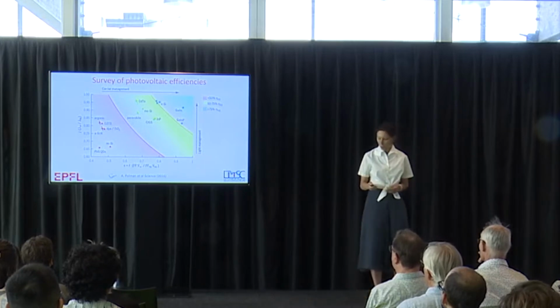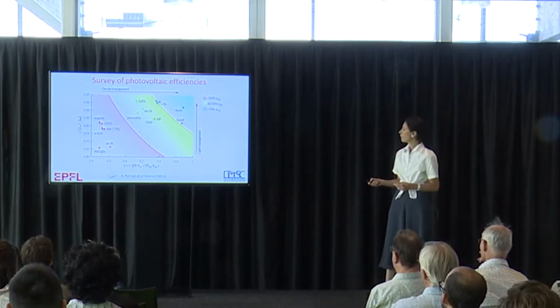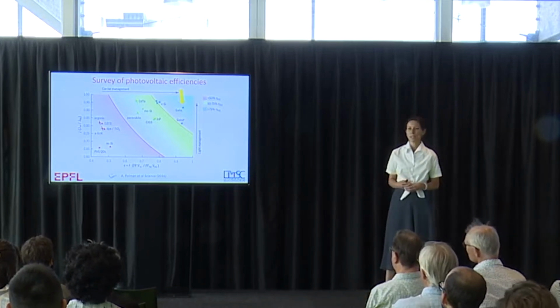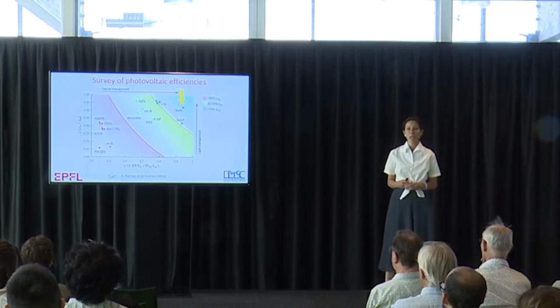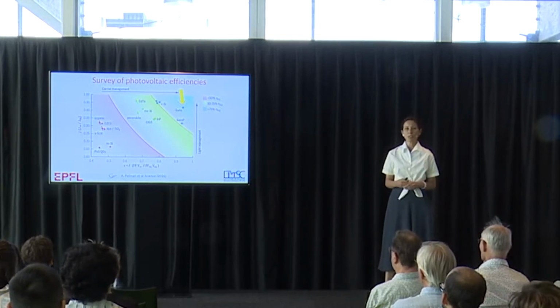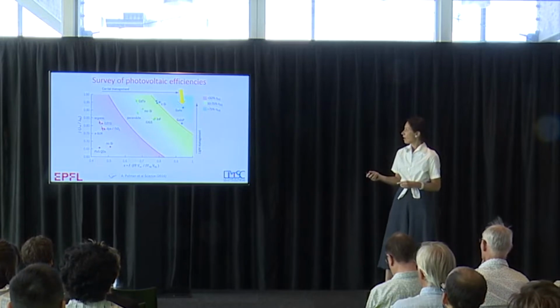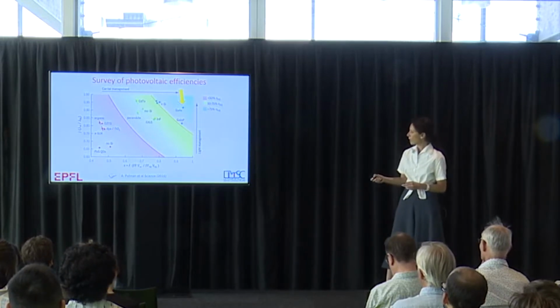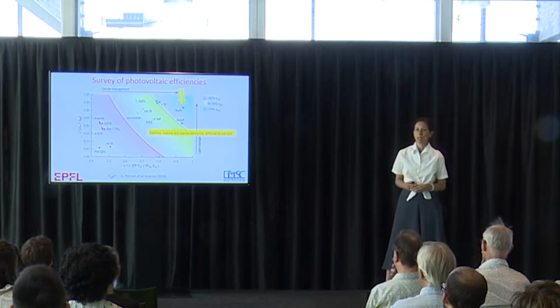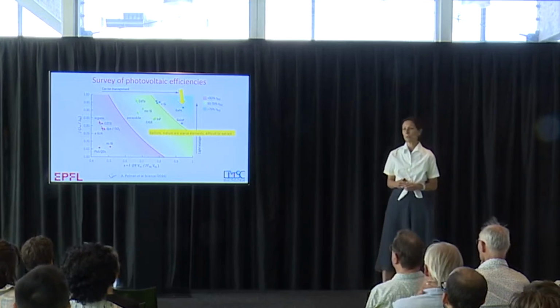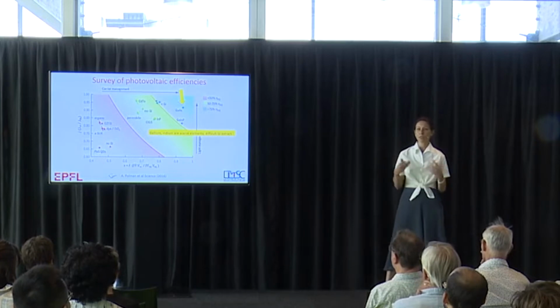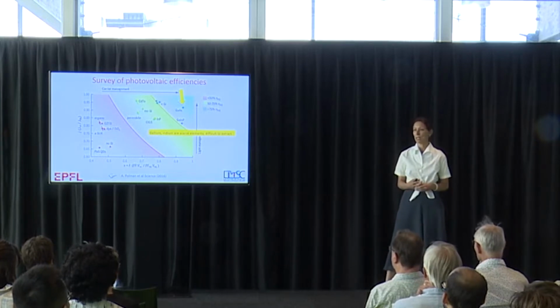And so in this graph here, you see that the king of the materials is gallium arsenide. It's a direct bandgap semiconductor. It has reasonable mobilities so that you don't have recombination. You have a very good material that can go. Still, gallium arsenide is made of gallium. Gallium is more abundant than indium, but it's very difficult to extract. So the cost to extract gallium is very high.